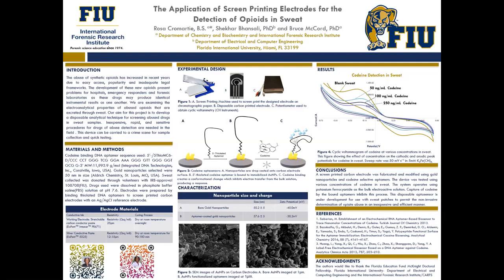And in figure 3, we have scanning electron micrographs to show the interaction between gold nanoparticles and aptamers at a size of 1 micron. The right image shows that when aptamers are functionalized on the gold nanoparticles, the size of the gold nanoparticles begins to increase, creating an enhanced cluster. As you can see, the left is smaller, and then the right is really big clusters of the gold nanoparticles.